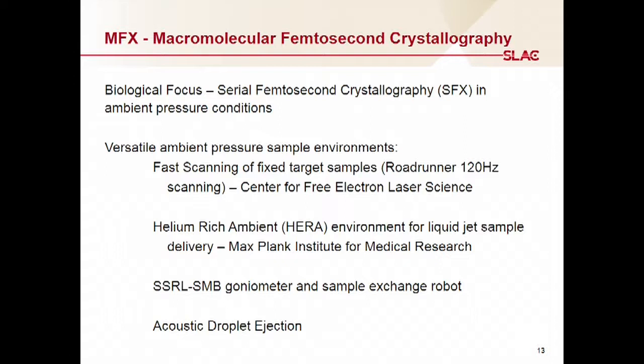If you do have a lot of sample, then you can use the helium-rich ambient, which is the HERA environment, which is just a helium environment that was built by the Max Planck Institute for Medical Research. There's also, if you have a single crystal that's a fixed target that you want to use with a standard goniometer setup, you can use the SSRL SMB goniometer. There's a goniometer, a sample exchange robot for taking bigger macromolecular crystals. There's also Acoustic Droplet Ejection, which is a drop-on-demand tape deck kind of device, which is also good if you have rare samples that you can't perhaps make enough to use a liquid jet for.